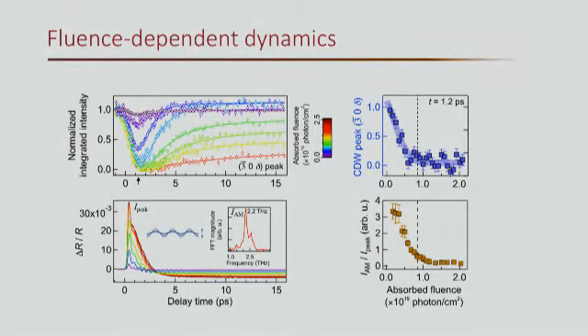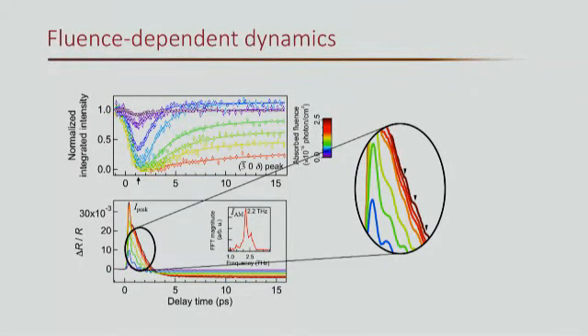But I also want to point out, despite the fact that it is pretty much saturated here, if we look really closely at these modulations, even at the highest excitation fluence, you can still see some wiggles. And if you do the Fourier transform, you can still extract the tiny remaining peak. So the modulation from the amplitude mode is always there, no matter how hard we pump. And if we fit this frequency as a function of fluence, no matter how much energy we put into the system, the frequency doesn't change. That means the amplitude mode doesn't soften. That is a bizarre phenomenon. I'm going to come back to it later.